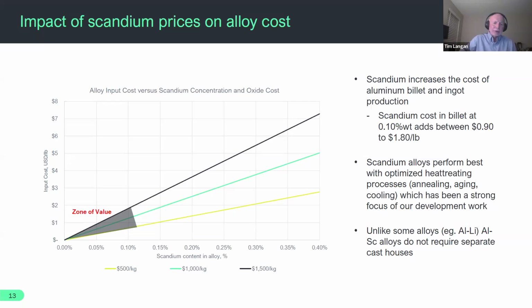And what we're looking at on the graph here is the effect of scandium level on cost in the billet. What we're showing here is the black line. These are different prices for scandium oxide. Historically, scandium oxide has been around $1,500 a kilo. At some points, it's been up as high as $5,000 a kilo. So what we're trying to do in our development efforts is lower the scandium level as low as we can to still maintain performance and optimize the cost.